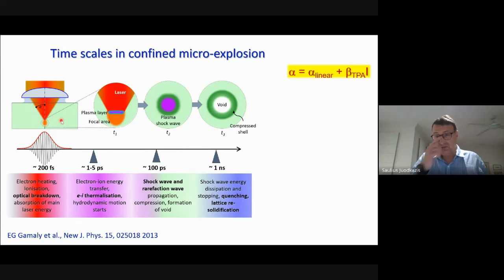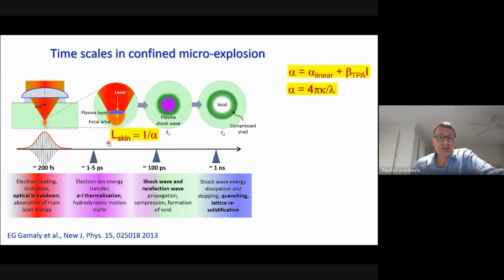And here is the only place where I show a few formulas, but this is really something extremely basic. Energy should be delivered if we want to modify material. So there is the absorption coefficient alpha, which will be linear. For transparent material, it's not a very big number, so light is passing through. Then we should have a nonlinear term, which is changing absorption. The first would be two-photon absorption, among many possible nonlinear terms. It depends on intensity, and that's why we call it nonlinear. And absorption, where we deposit energy, depends on alpha, so it will be the skin depth, which is just the reciprocal of alpha.